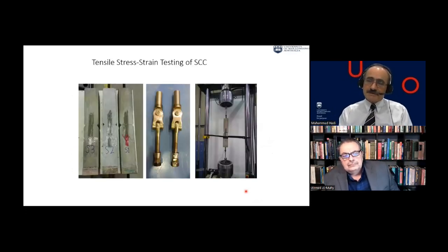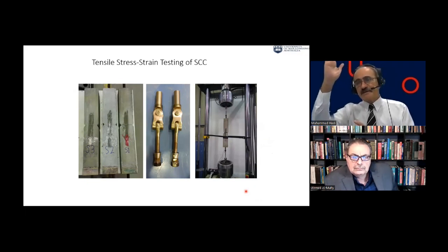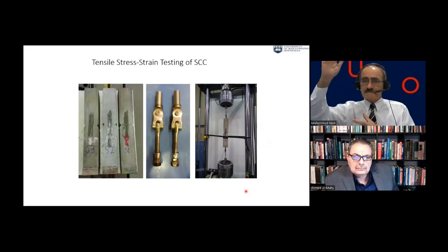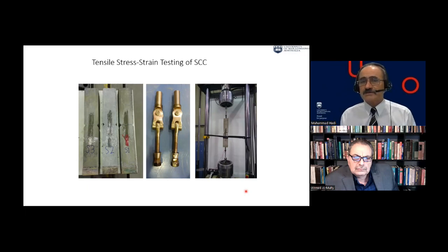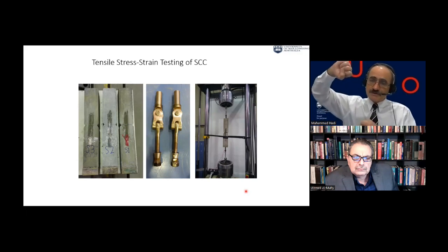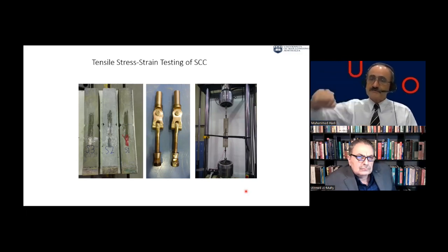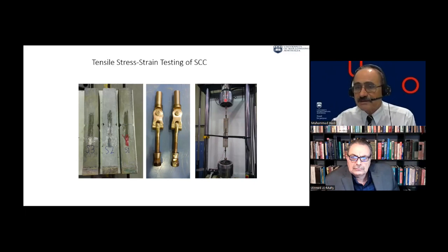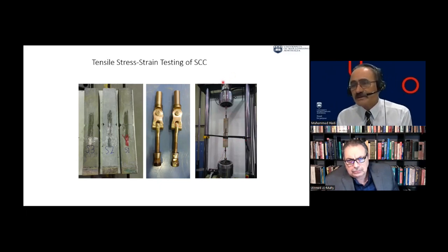The problem is, because you are dealing with material which is very weak in tension, and there are some problems, we wanted to have perfect alignment. So we built universal joints, and those joints will adjust themselves. And you can see we are testing in the same machine, the 2-meter high machine. And we put those and we tested them. We published this work in Construction Building Materials.